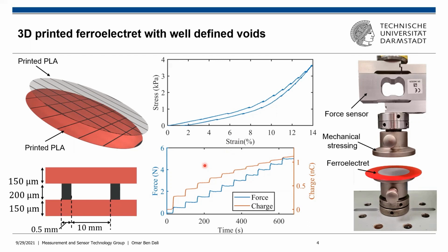When the force increases from 0 to 0.5 Newton, a piezoelectric response of approximately 600 picocoulomb per Newton is recorded. This response, however, decreases with each force step to attain the minimum value of approximately 120 picocoulomb per Newton, starting from 2.5 Newton. This value is then maintained for the rest of the steps.